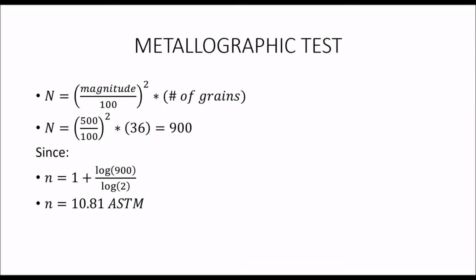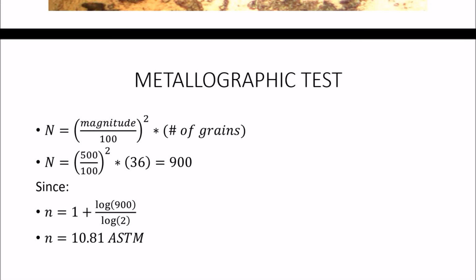Here you're watching the analysis of the quantity of grains that we saw in the other picture. The number of grains that I detected was 36 grains. So the magnitude here is 500, and we are dividing by 100 and multiplying this number by the number of grains. So the result was 900 grains, and to obtain the grain size number in ASTM, we use the second formula, and the value was 10.81 ASTM.